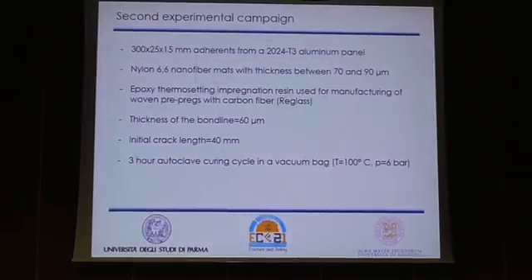A second experimental campaign was performed in order to limit the level of porosity. The curing cycle occurred under vacuum, and an epoxy thermosetting impregnation resin used for manufacturing woven prepregs with carbon fiber was used instead of the more viscous epoxy film, in order to make the resin flow into the whole thickness and to fully impregnate the nanomat.